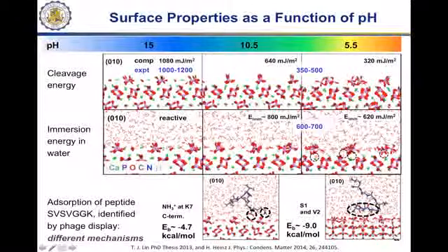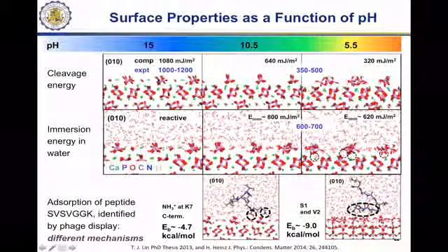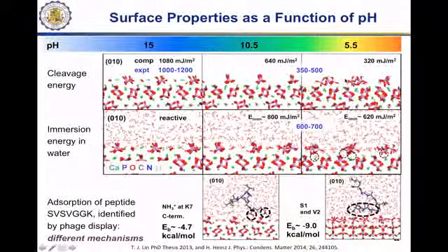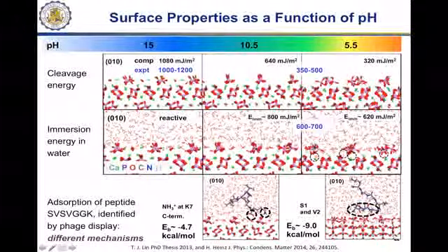On a more fundamental level, cleavage energies are tremendously dependent on protonation of the surface. The more it's protonated, the lower it is, and the correlation with experimental data is pretty good there. Hydration energies or immersion energies in water also, expectedly, change a lot when you have different degrees of protonation.